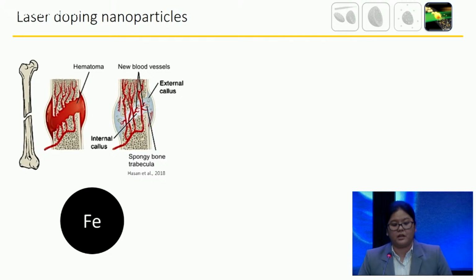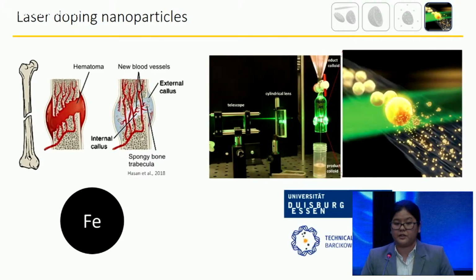Ion incorporation in the MSN and bioactive glass via wet synthesis has many disadvantages. Only so many ions can be incorporated before negatively influencing the particle formation. Especially, the incorporation of copper ion is difficult. However, the ion plays an important role in stimulating blood vessel formation, which is vital for transportation of nutrients and ensuring proper bone regeneration. Therefore, we explored an alternative synthesis method to incorporate multiple bioinorganic ions into the solid bioactive glass nanoparticle using laser doping technology. This technique was performed by our collaborator at the University of Duisburg-Essen in Germany.